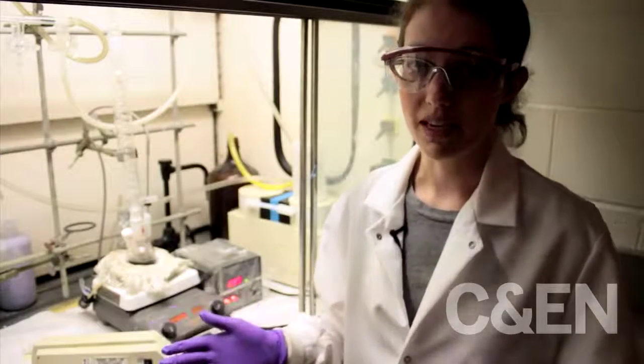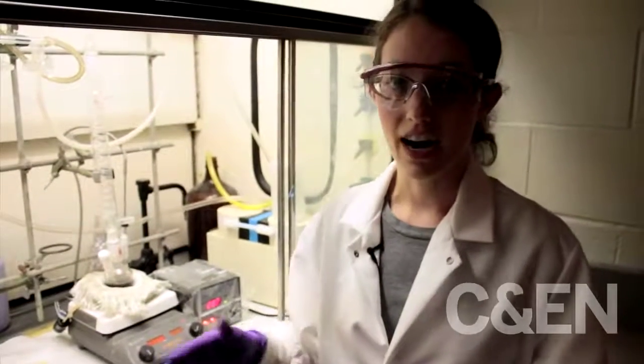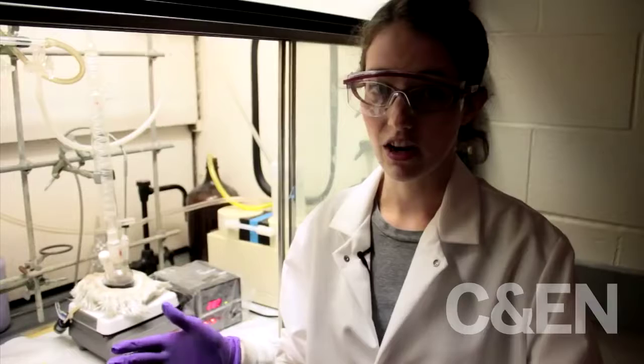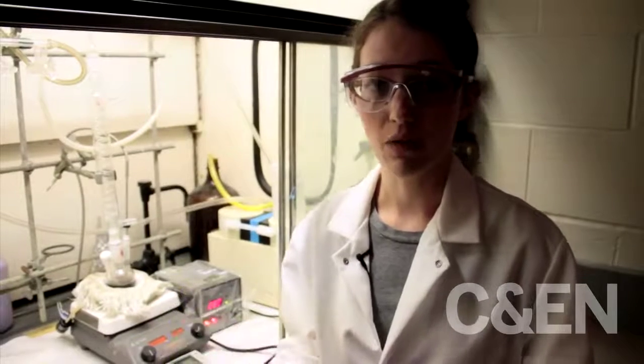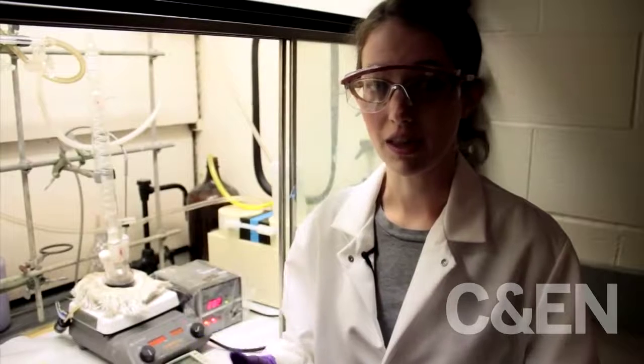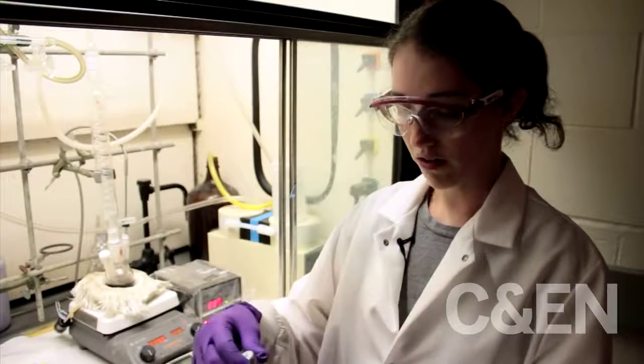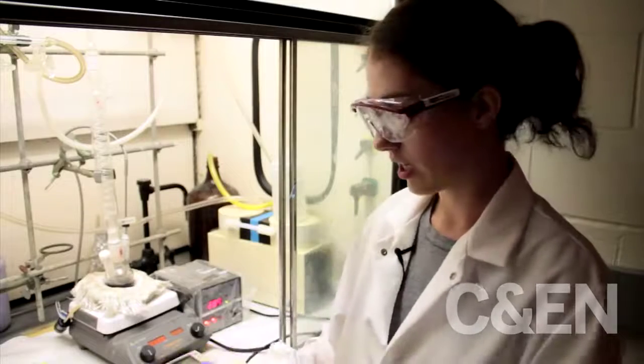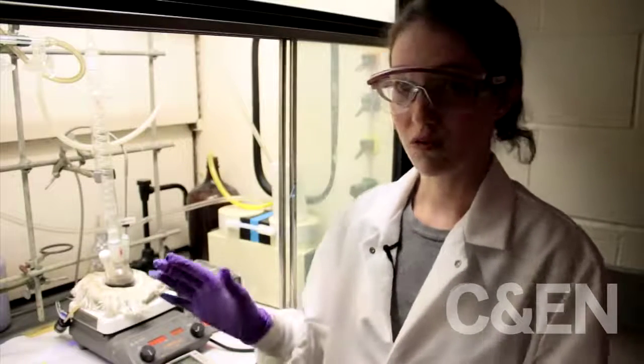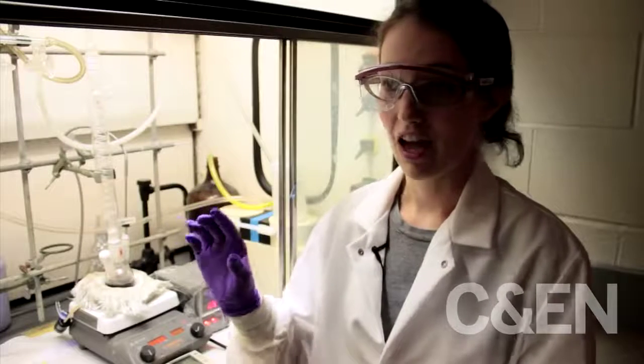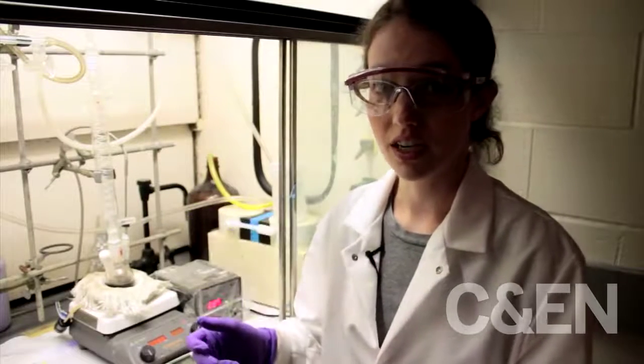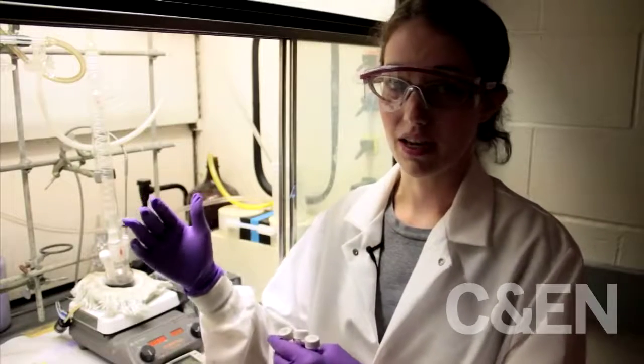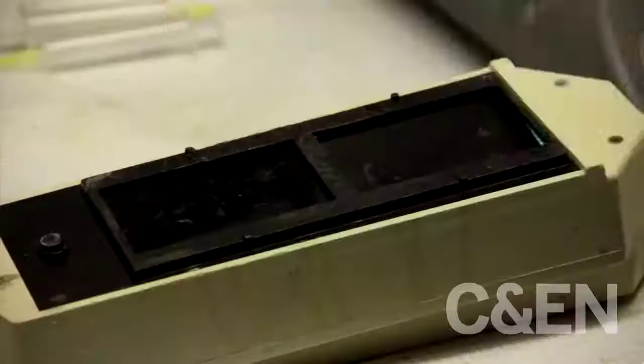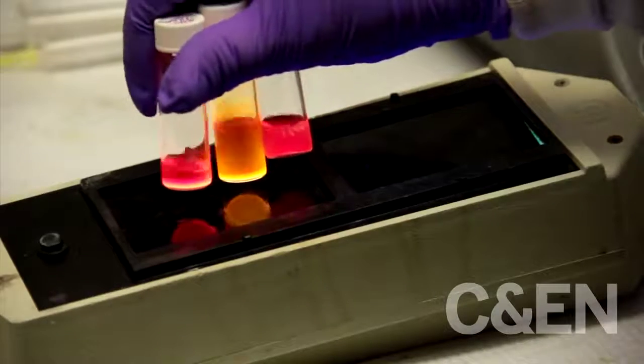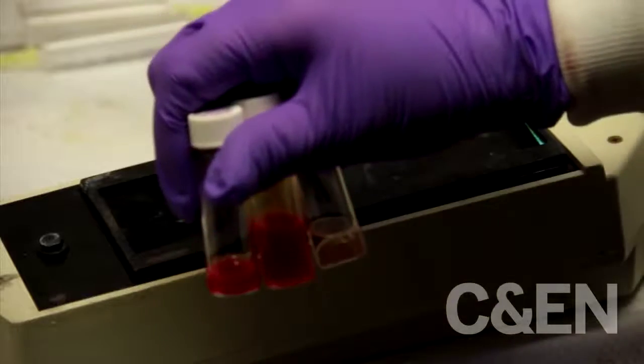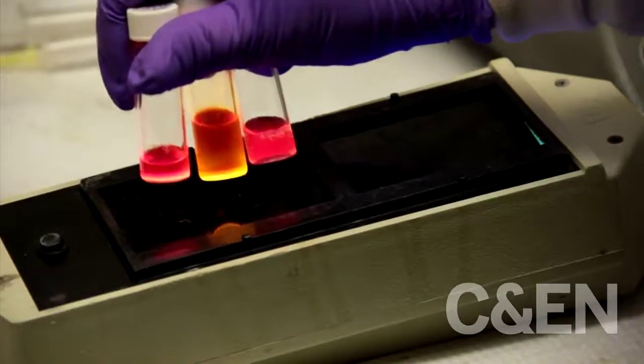And these we can tailor to be different colors, but these are in chloroform or hexane. They're in an organic solvent, and if we want to ever use them with things in the body, we need to put them in water. In order to put them into water, we end up usually with a much more dilute solution, and we cover them with lipids, which basically are two components. They coat the quantum dot with the hydrophobic portion, and then the exterior of the lipid is hydrophilic or water-loving. And you end up with something like this. The reason they fluoresce is because they're excited with the UV light. So when we take away that UV light, they no longer glow.